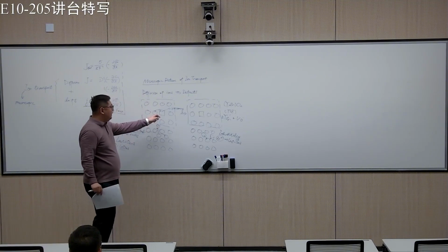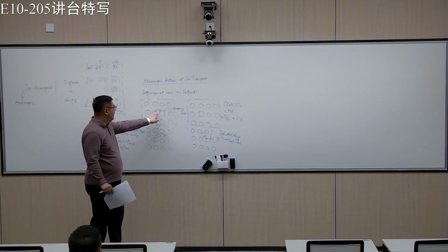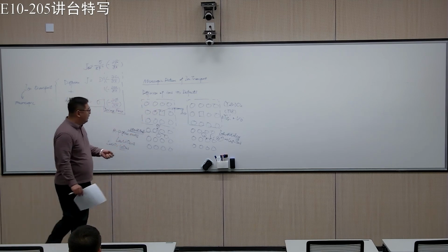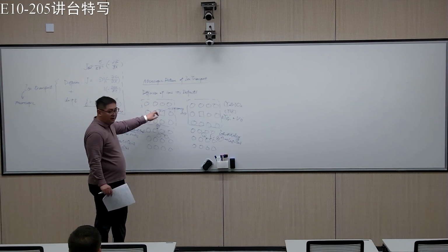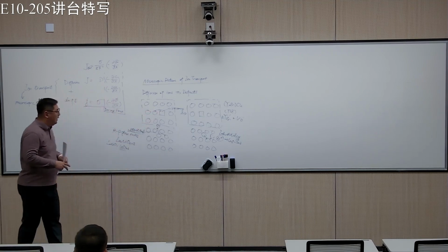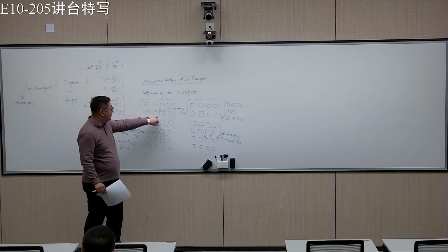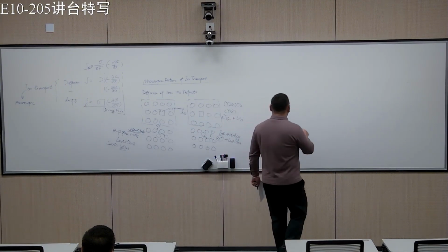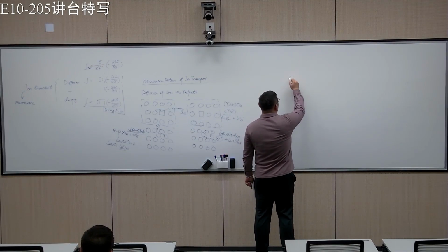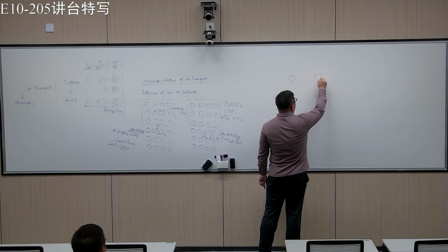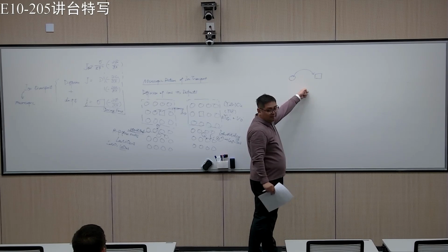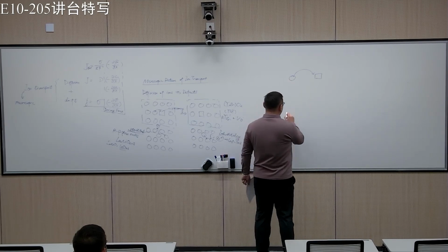Sometimes in between the two states, there will be a moment when the ion is in an intermediate position. Usually, when the ion is in the intermediate position, it really perturbs the ion potential of the lattice, and the energy really goes up. So if you have an ion here, and you have a vacancy here, then if you jump from here to here, in the middle, you have to overcome some kind of barrier.